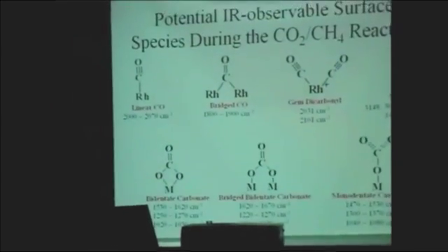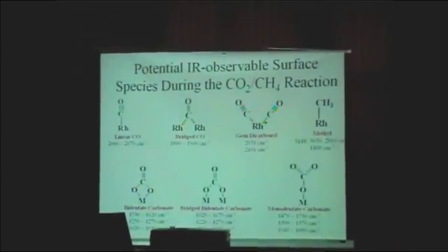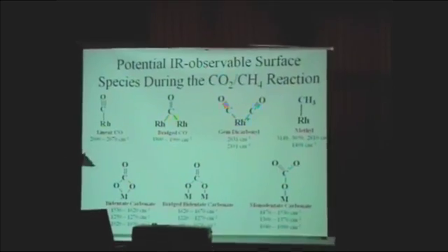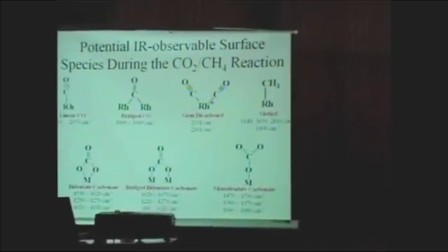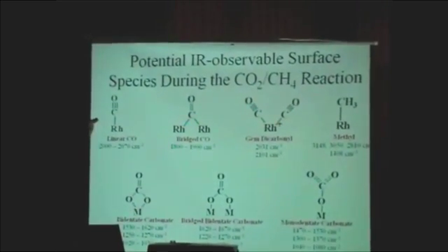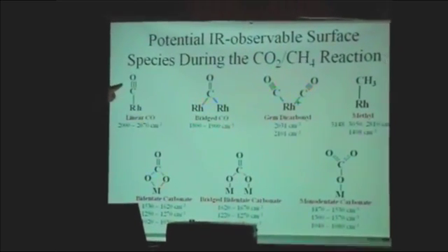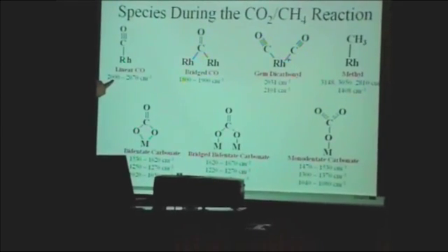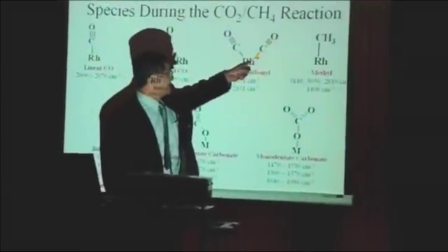So infrared is an ideal tool to characterize the catalytic surface under reaction conditions, simply because infrared can penetrate through this reactant environment. Whatever reactant is adsorbed on the surface, if it is in polar form, it can be detected by infrared. And in this case, if the rhodium is in the reduced state, it is going to produce CO with a wave number above 2000. If rhodium is in the oxidized state, then it is going to give you the gem-type carbonyl species.